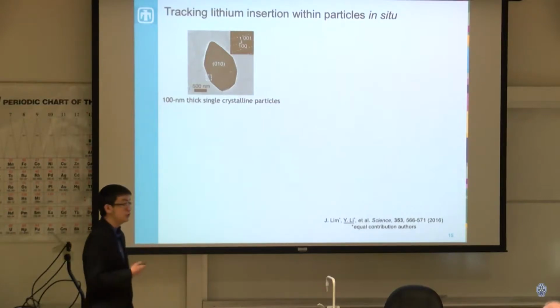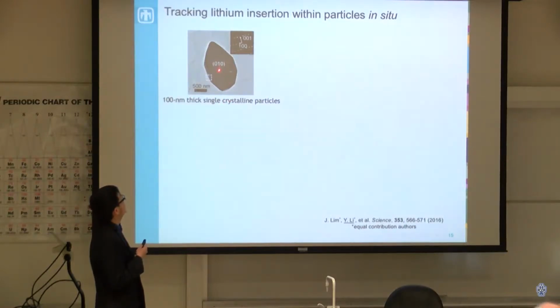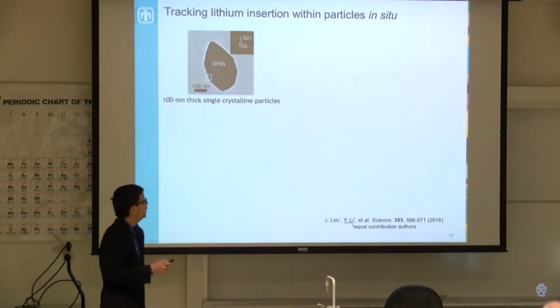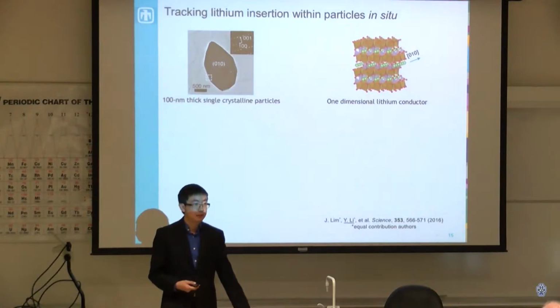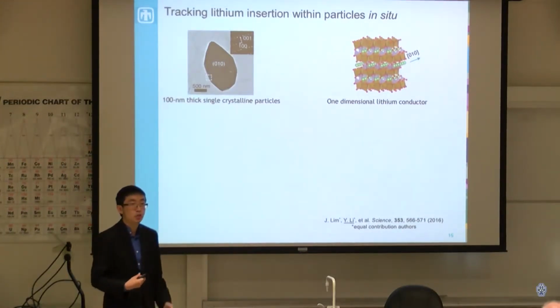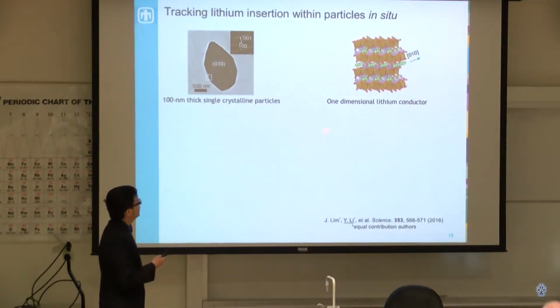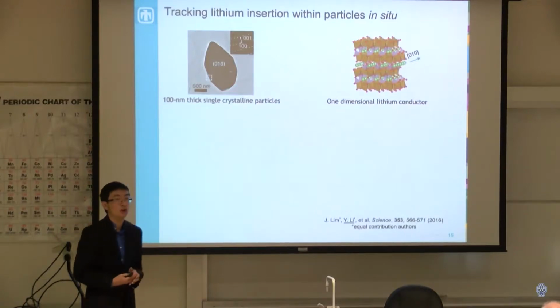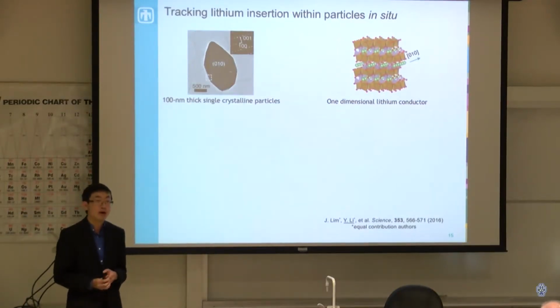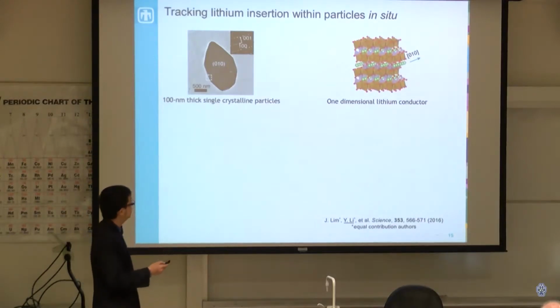So our work is to use these single crystalline battery particles, so they're just about 100 nanometers thick, but they're a little larger in aspect ratio. So I have these microplatelet particles. One important thing to note about this material is that it's a one-dimensional lithium conductor. Whereas some materials are isotropic, typical metals like iron and nickel, this material is anisotropic. So I have this orthorhombic crystal structure, and it's arranged in such a way that lithium can move very fast along the 0-1-0 direction, so into the page direction, but it moves excruciatingly slow in the other direction, about 10 orders of magnitude slower in the other directions compared to the fast direction.